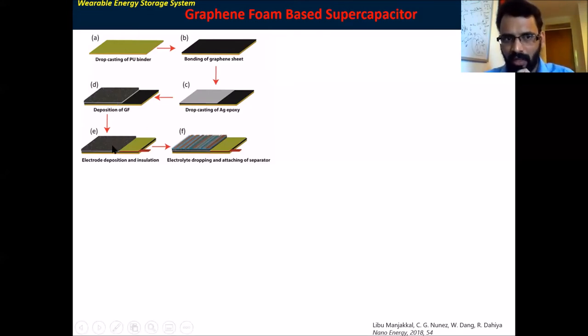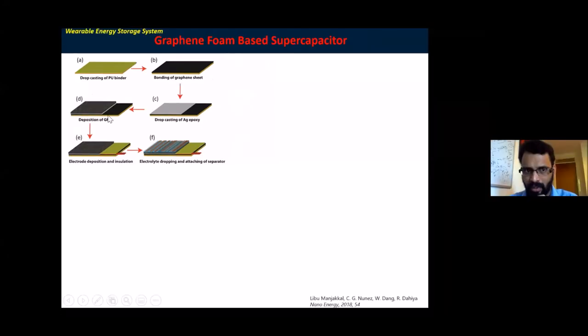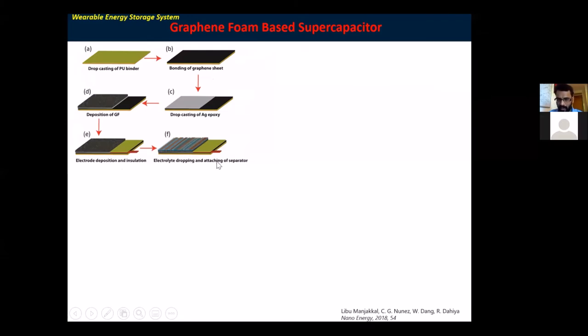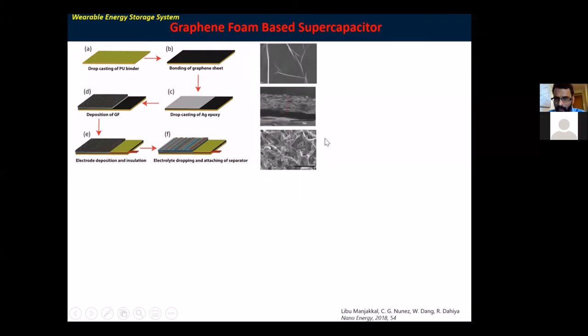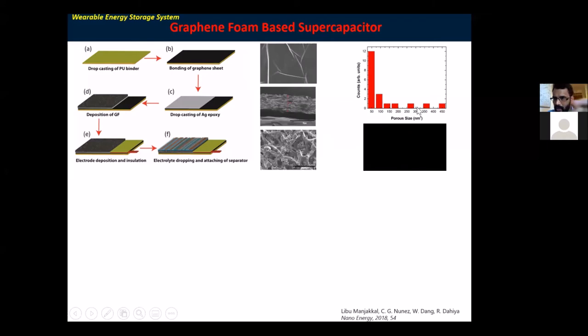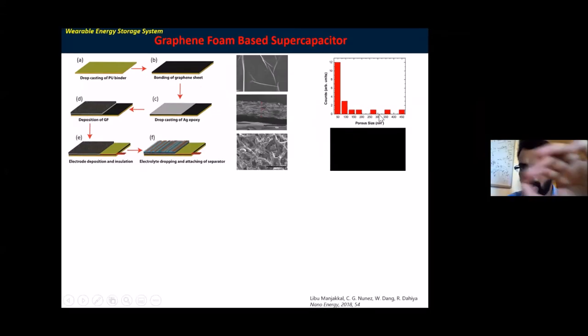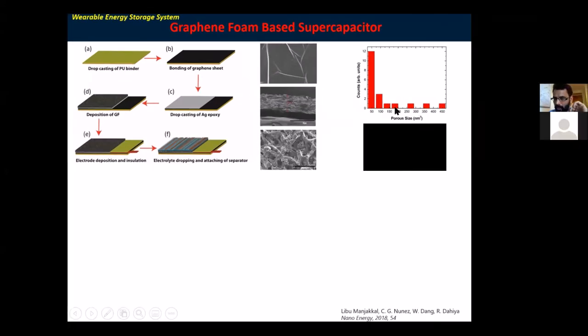I used a freestanding graphene foam attached on top of this graphene sheet, as you can see here. Then on one side, I applied an electrode for the external current collector and then an insulative epoxy to protect that, and then dropped an electrolyte here. As you can see, the top figure is a graphene sheet and graphene foam structure. You can see a 3D network structure and porosity, because these ions can easily diffuse into the material. So porosity analysis is one of the most important things. You can use BET. Here I used ImageJ software.